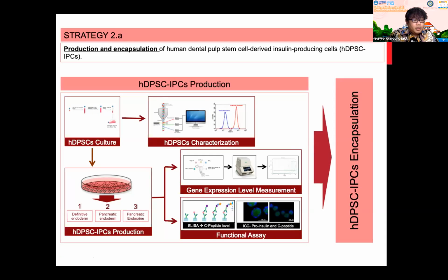In this strategy, the human dental pulp stem cells were cultured. I think Dr. Chen Pop and Dr. Watchareewan already mentioned a lot about this. This one is just the IPC production, starting with the culture of mesenchymal stem cells, and then doing the characterizations, and then using the optimized protocol that was already established in our laboratory. We just use the most simple protocol. We just use 3-stage differentiation or microenvironmental manipulations without any genetic modifications. After that, we evaluate the gene expression level measurement by RT-qPCR, and we did the functional assay by using the ELISA to check the C-peptide level, and also the ICC for checking the proinsulin and C-peptide as well.